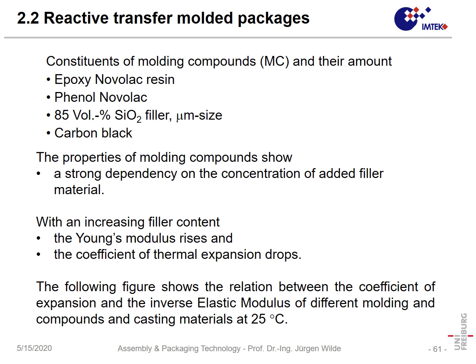So, summarizing reactive transfer molded packages, the constituents are typically epoxy Novolac and phenolic Novolac resins. We have a high degree of silicon oxide fillers, which are in the micrometer size. Another material which is added is carbon black, because we know almost all molding compounds are black. The properties of the molding compound show a strong dependency on the concentration of the added filler material, and of course also a strong dependency on the type of resin. With an increasing filler content, the Young's modulus rises, and the coefficient of thermal expansion drops.